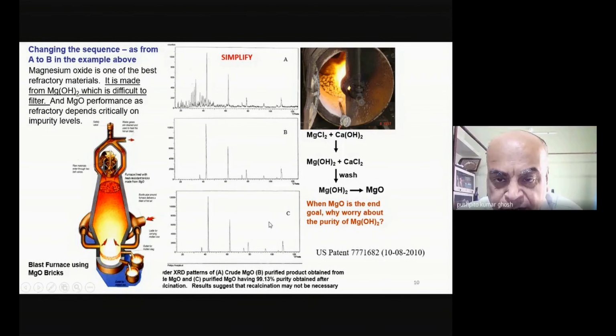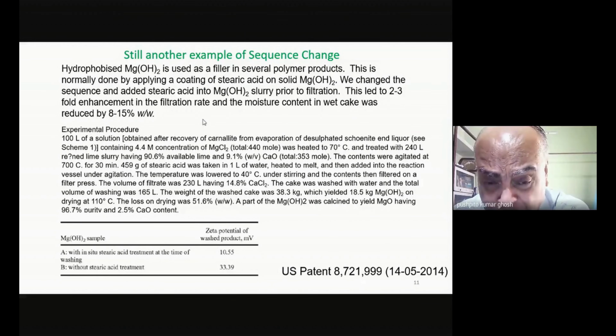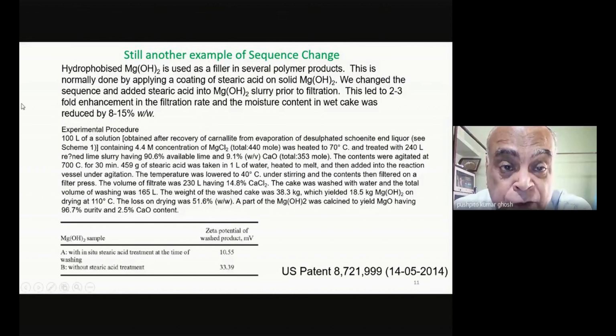Take another case, again related. You can use magnesium hydroxide either to make MgO, or magnesium hydroxide is also used as a fire retardant, in a lot of things where there is a fear of heat development, cables and things like that. Typically, because Mg(OH)2 is not directly compatible with plastics, it is too hydrophilic, the Japanese found a way of putting stearic acid on the magnesium hydroxide, coating it, and made it hydrophobic. That happens because of the acid-base reaction between the magnesium hydroxide, which is basic, and stearic acid, which is acidic. So it forms a coating, and then it becomes easier to incorporate it uniformly in plastics.